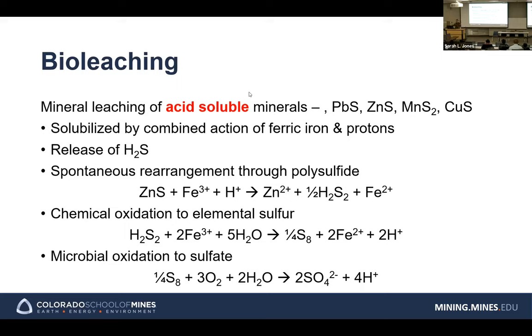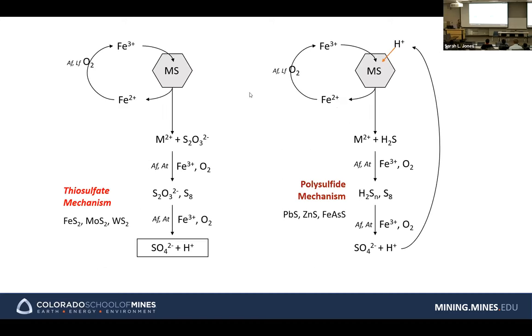And then also I mentioned Fe3 plus is going to reduce to Fe2 plus. And how do we get those Fe2 plus back to Fe3 plus? That's one of the bio reactions in the microbial system. So this slide summarizes those two things. So you have a metal sulfide, and it's leached by the ferric ion. So ferric ion leaches the metal sulfide, and it's going to reduce to Fe2 plus. And then from the metal sulfide, you're going to have a metal cation and a thiosulfate or H2S. And then also this Fe3 plus and oxygen further oxidize the sulfide, sulfur complex, all the way to sulfate and hydrogen ion. The intermediate is a little different, but at the end, we have a sulfate ion and a hydrogen H plus ion, a proton.